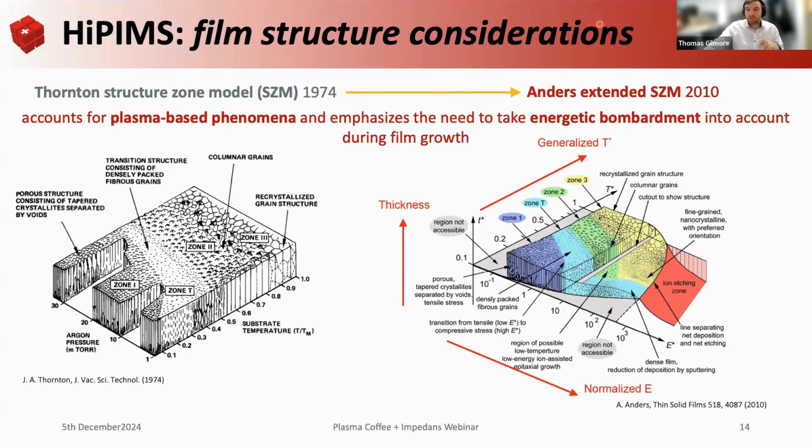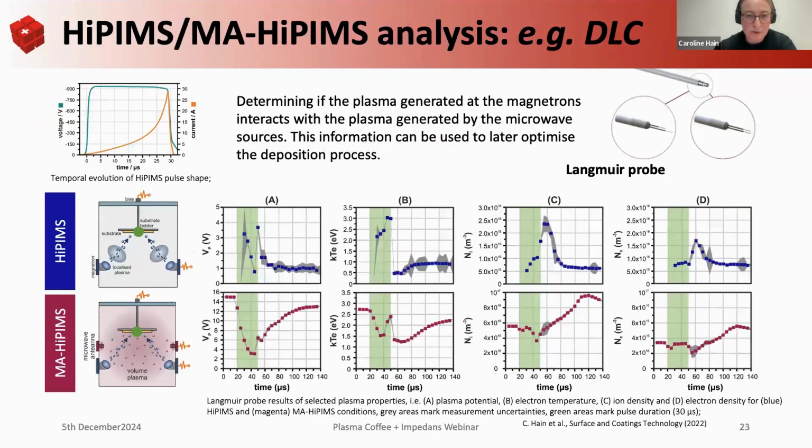We got a question regarding slide 23, which is on the Langmuir probe data. Yes, let me go to 23. I guess it's about the Langmuir probe surface coating. Yes, if we put in the Langmuir probe and then we sputter, then we also coat our Langmuir probe. So we would only have the sputtering process on while we were measuring, to reduce this as much as possible.